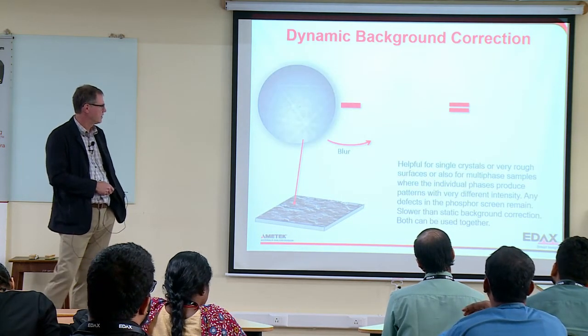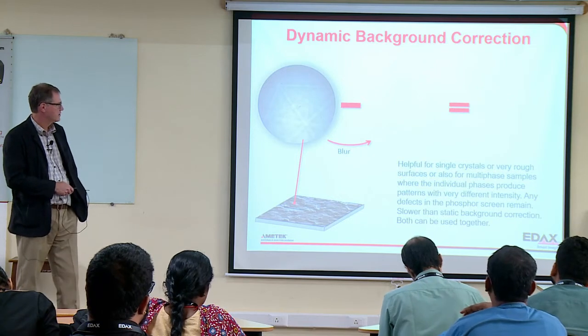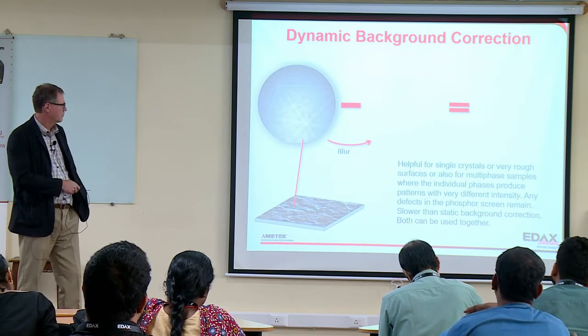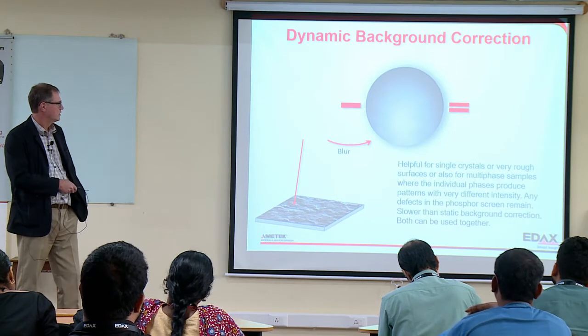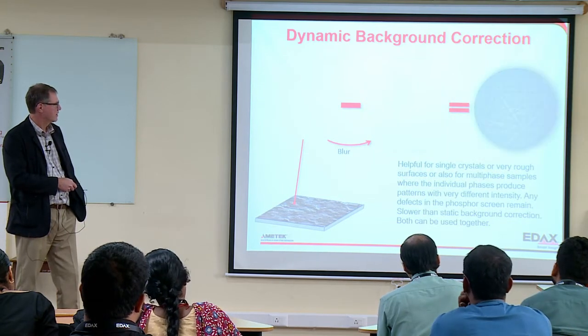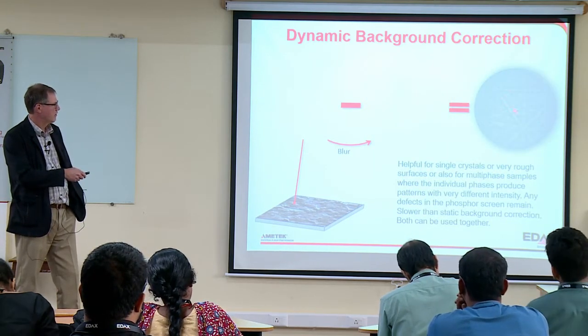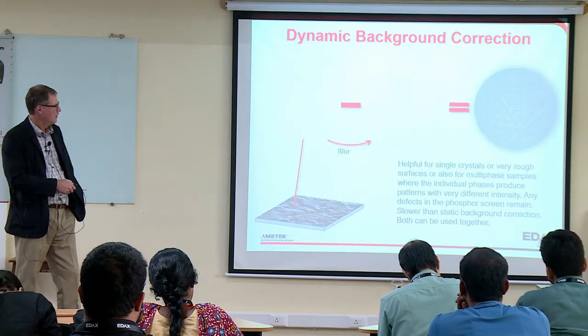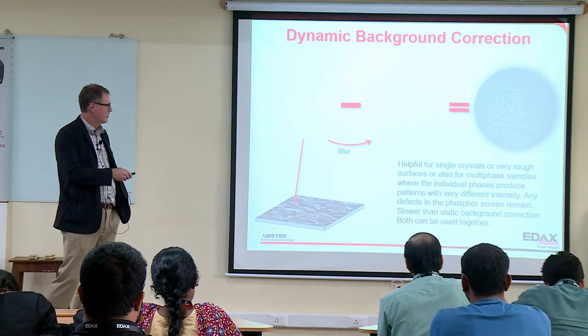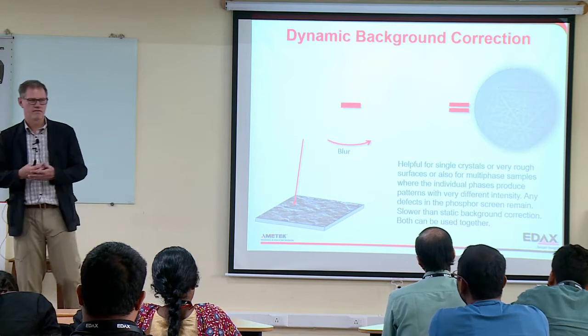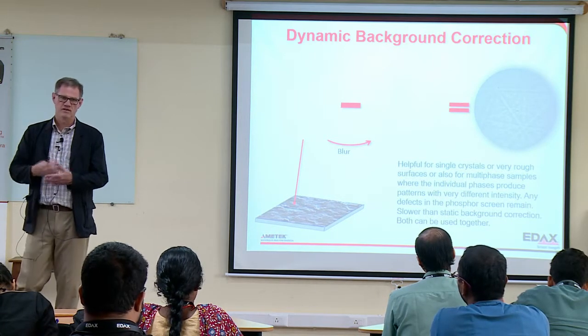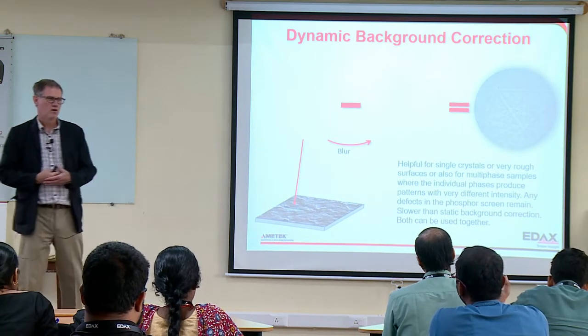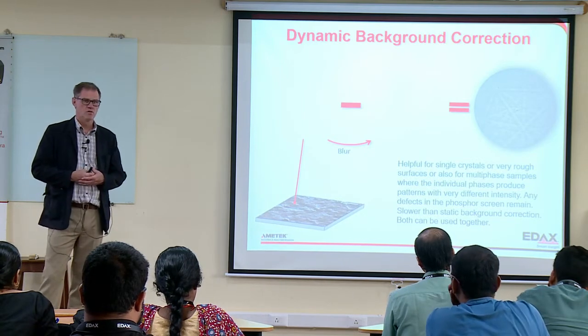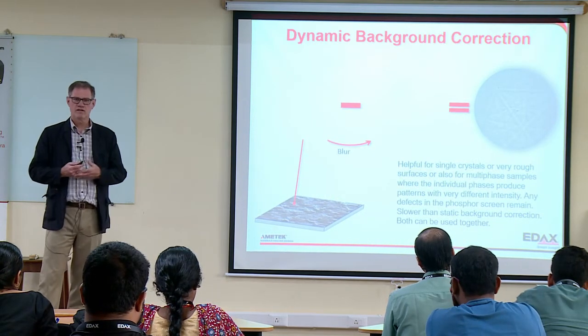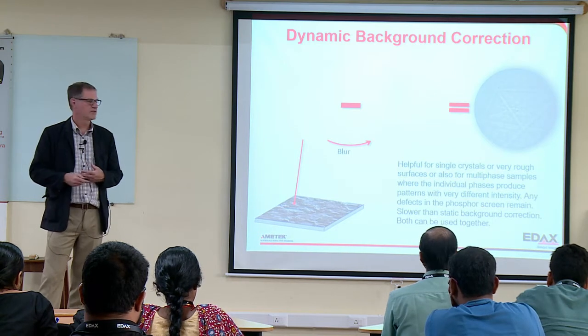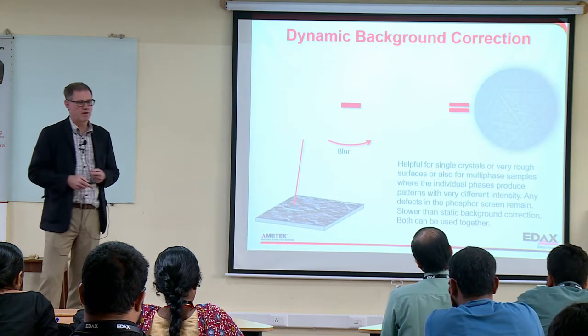There's another way to do this, and that is to use the pattern itself. So here's the pattern from an individual grain. We blur it, and then we subtract that. And then we get this nice pattern here. This is good if you have multi-phase samples where the diffraction intensity differs from phase to phase, or maybe you have very rough samples where the gradient is moving a lot from point to point because of the rough surface, then you might want to use this dynamic background correction.